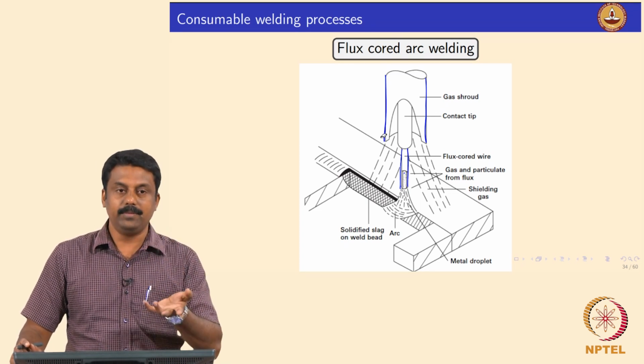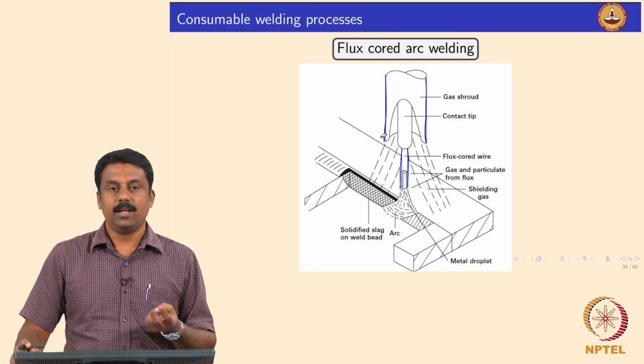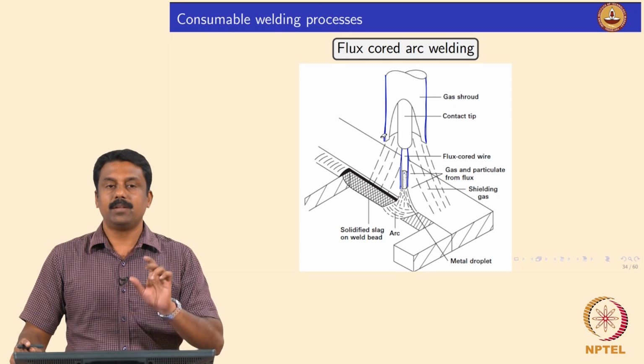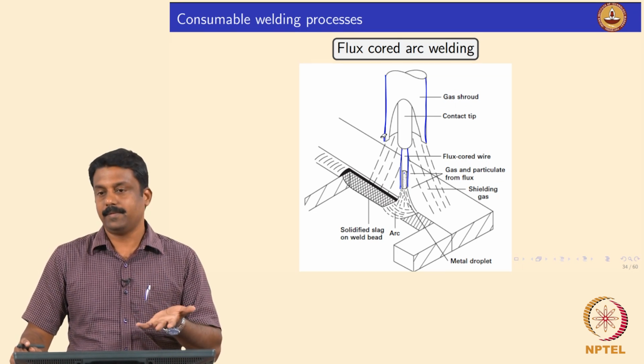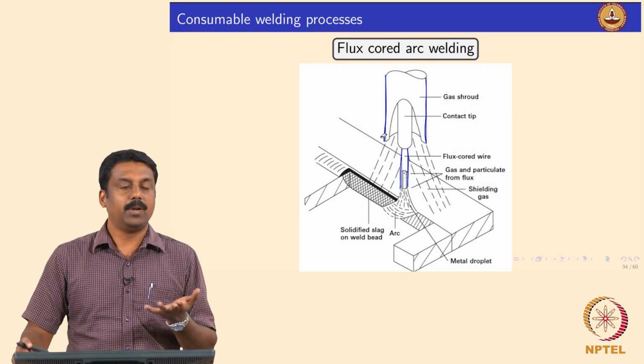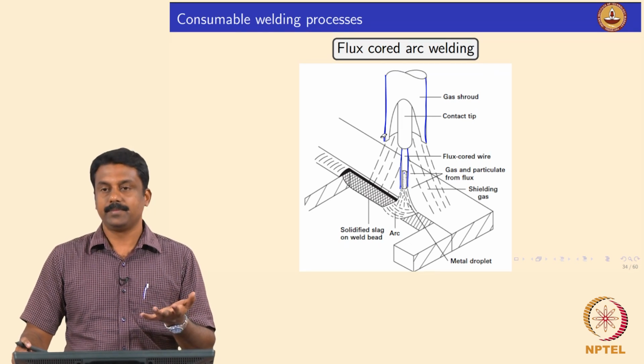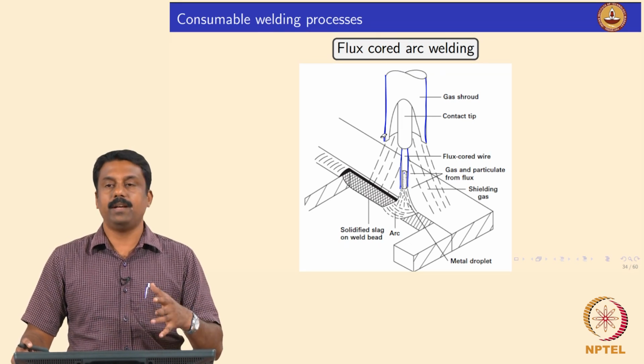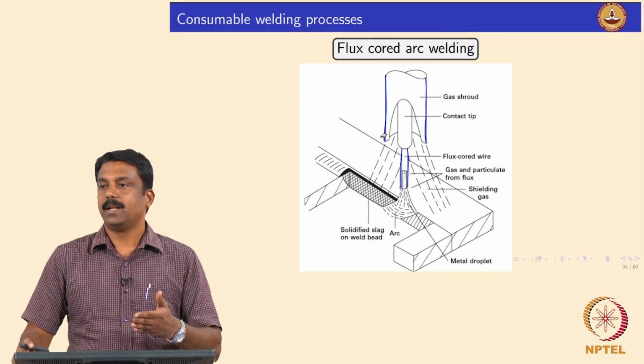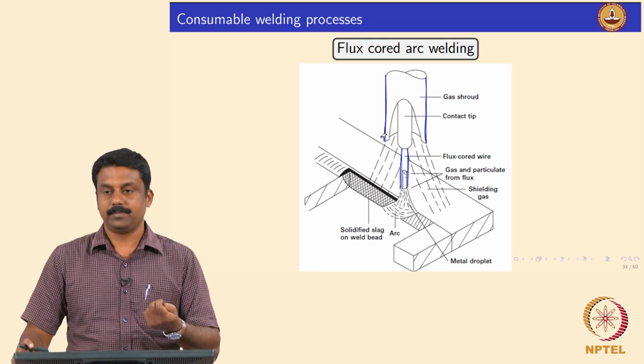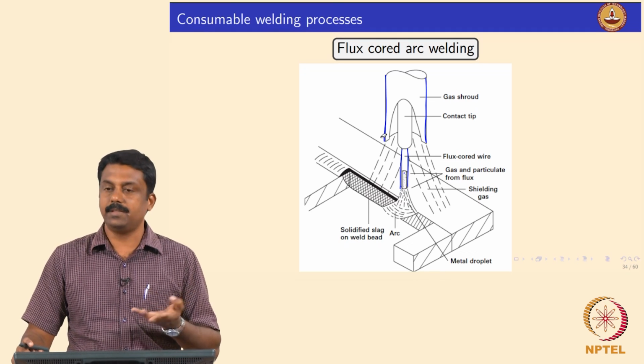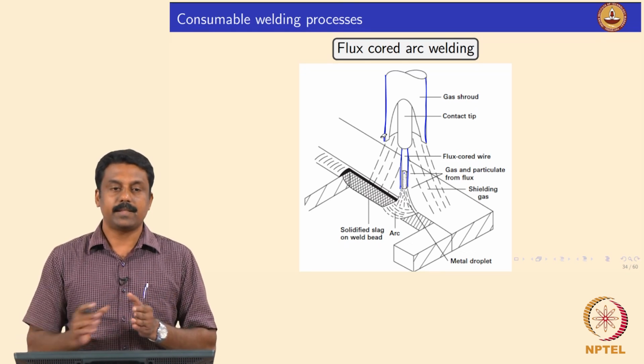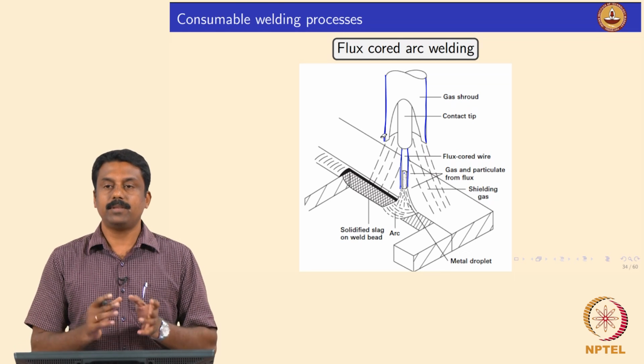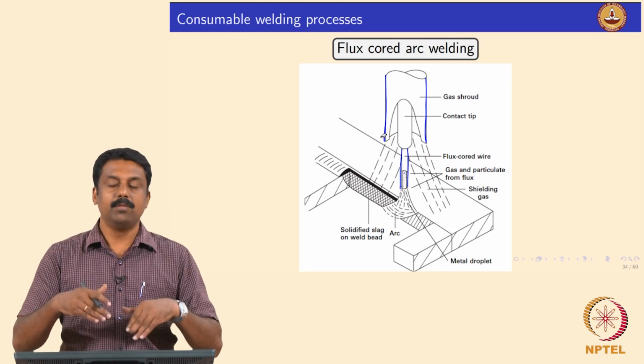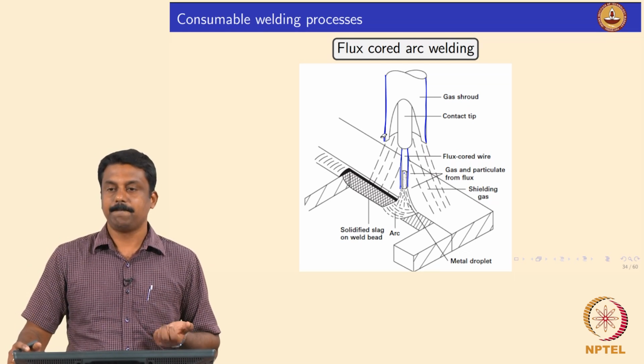Okay. So, in SMAW in most of the cases we do not use shielding, it is all self shielded, whereas in flux core arc welding we can also play around with the composition of the flux. In some cases you want to have maximum alloying, so you want to reduce the concentration of the flux, especially calcium carbonate for example. Then the shielding gas which you generate is not sufficient to have a sustained arc. So, this process can also be shielded by external shielding.